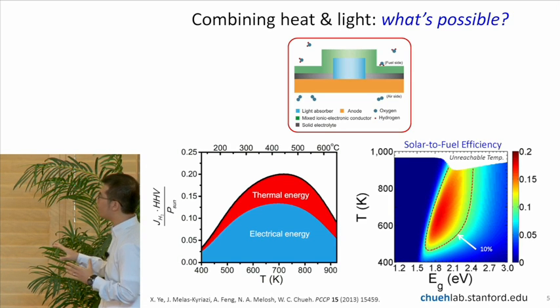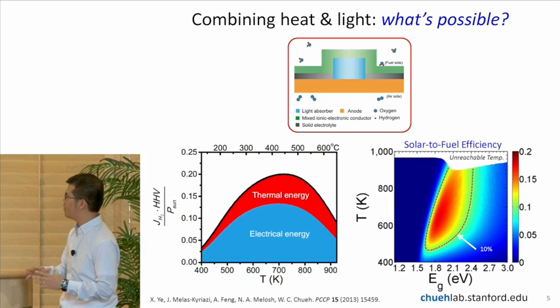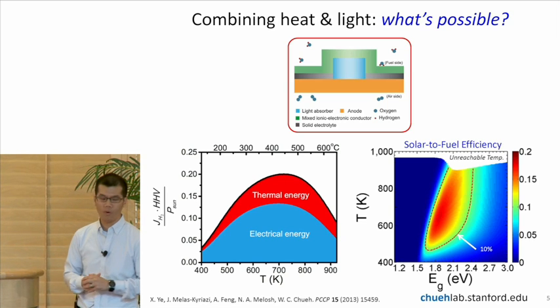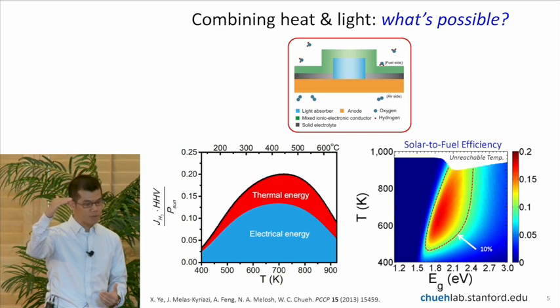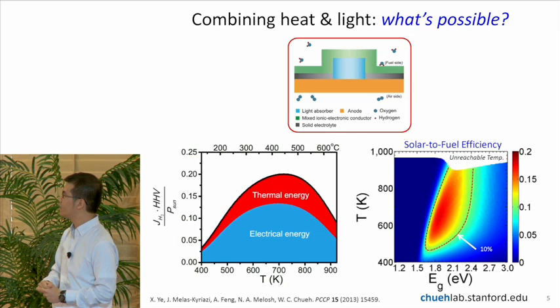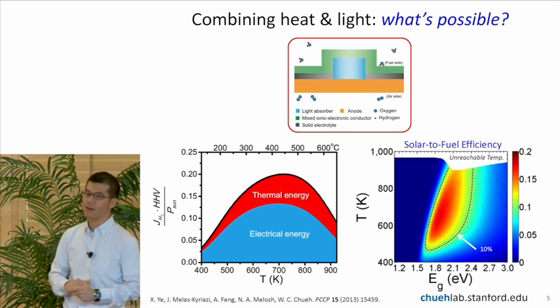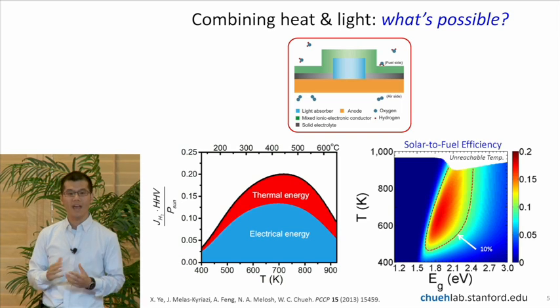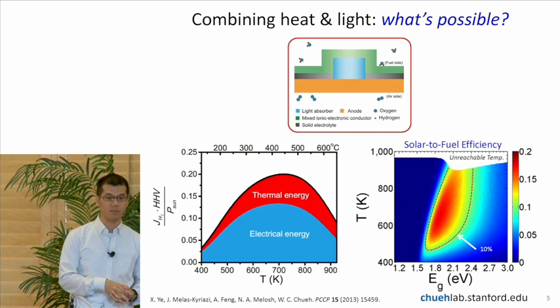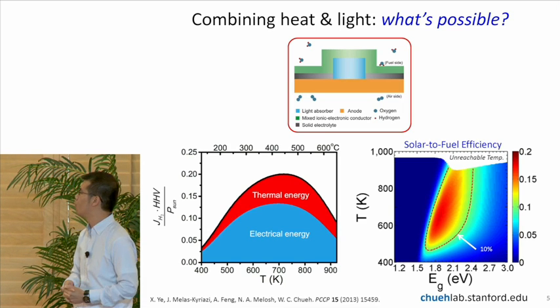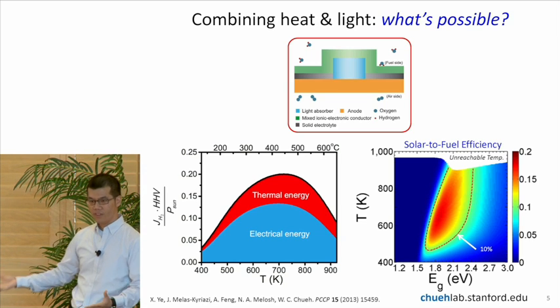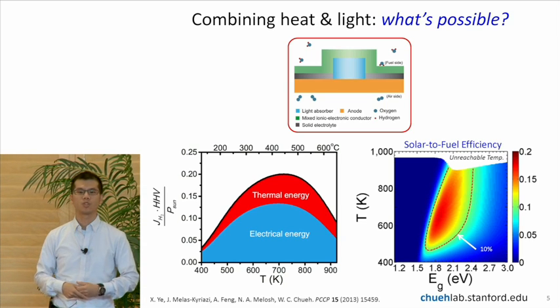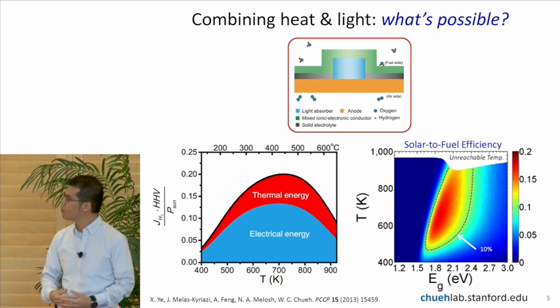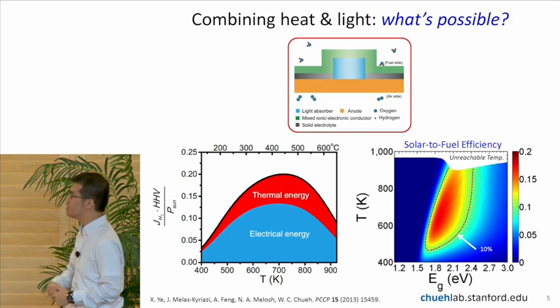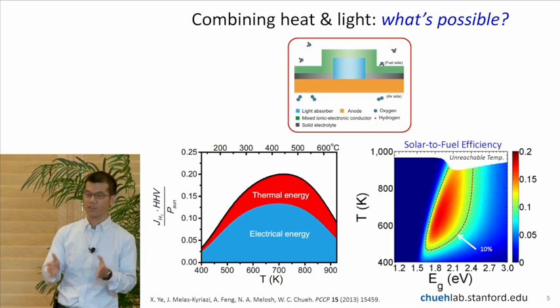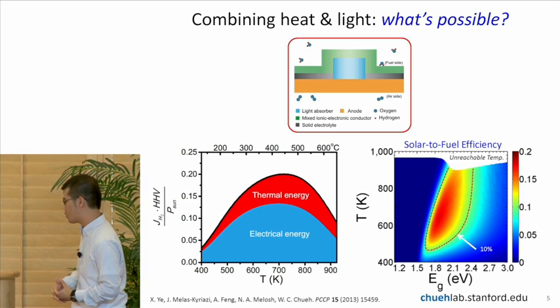And this contour plot shows that at intermediate band gap, approximately 1.8 to 2.4 electron volts, and at elevated temperature, 800 Kelvin, you can actually hit the sweet spot of the solar to fuel efficiency. And we estimated upwards of 20% as possible, which is a significant step beyond what we can do today. So with the theory understood, then we begin to explore actual material that can enable us to get to these temperatures of interest so that we can harvest both the thermal energy and the photon energy as well.